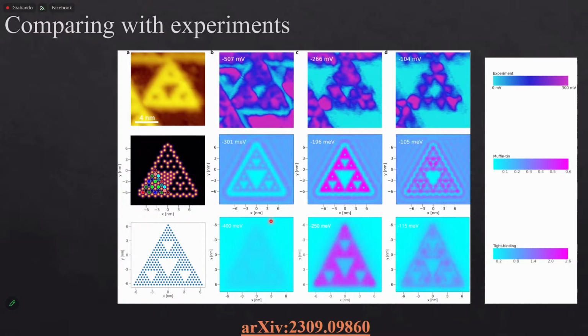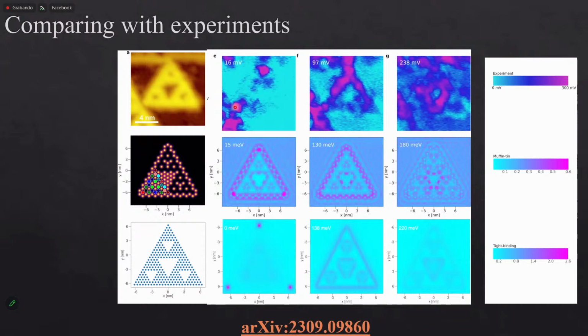For both the tight binding and the muffin-tin, we are keeping the same value of maximum in the density of states. So some features cannot be so clearly seen, but you're going to see that they look very close to the experiments. Here it's not so visible, but there is occupation in the bulk. The same here. What's more, these states at low energy are just bulk states and not so interesting. While close to the Fermi level, we start to see states that are localized in the corner. Here it's quite close to the corner. There's a corner state at 15 meV, and here at 0 meV in the tight binding model.